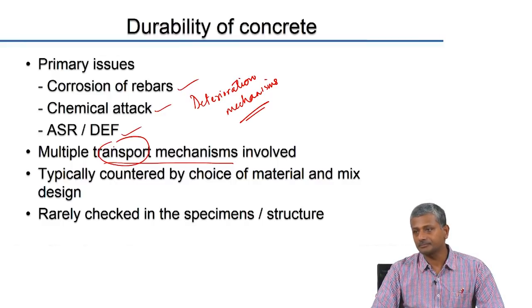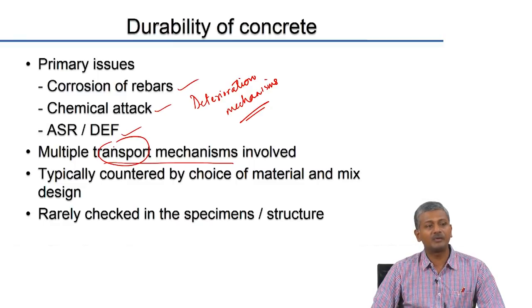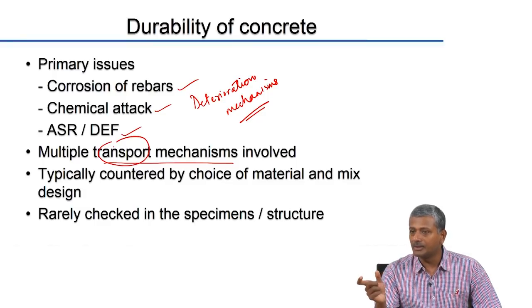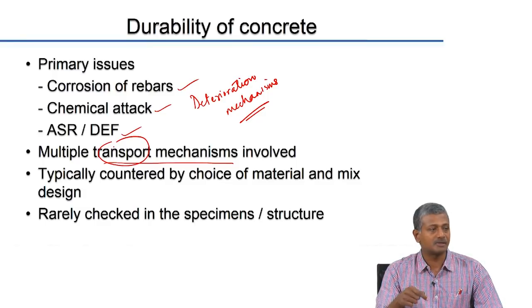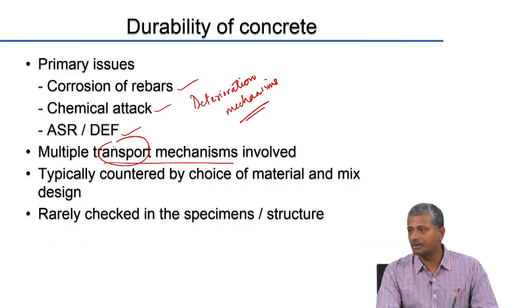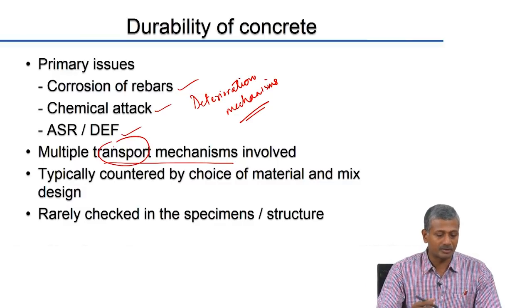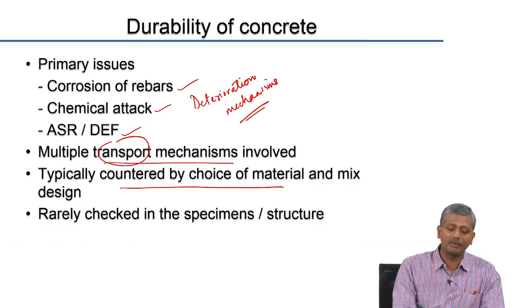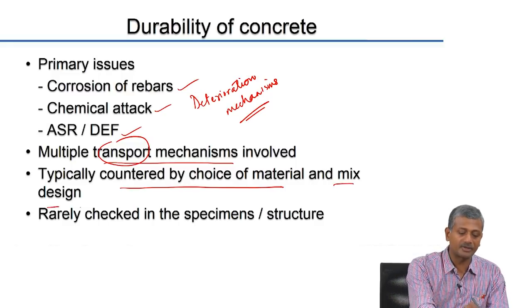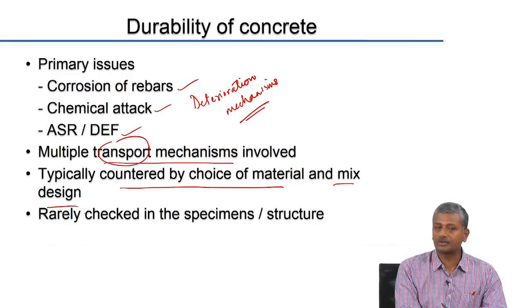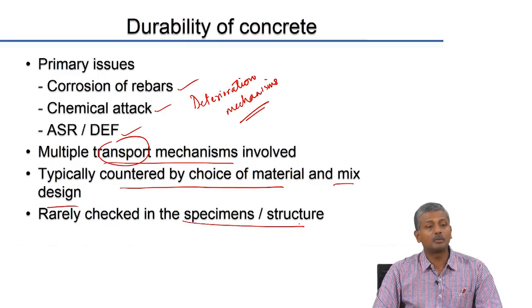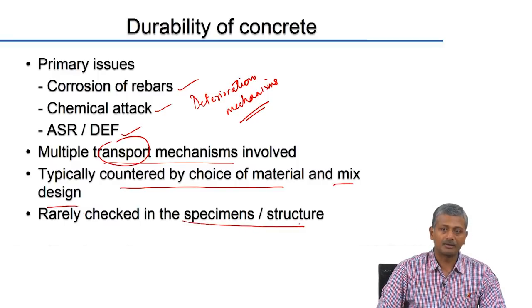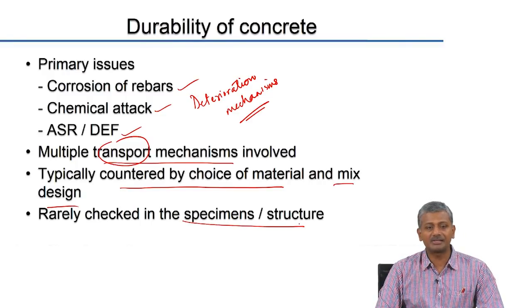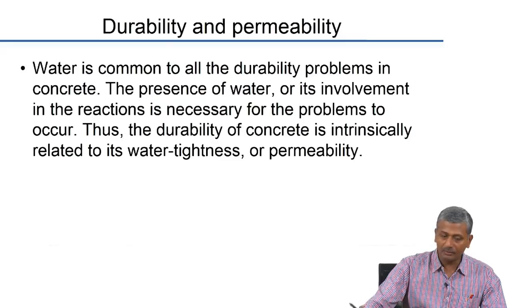Okay, so very often in the lab we study durability by measuring only one transport parameter. In reality, whenever a durability problem manifests itself in concrete, it is because of a combination of different transport mechanisms. Typically we design for durability by choosing the material appropriately and the amount of the material in terms of the mix design. But the problem is, once the concrete structure is in place, we do not really check the durability in the specimen or the structure. We check the strength and we assume that everything else depends on the strength. Okay. So, that is how we look at this.